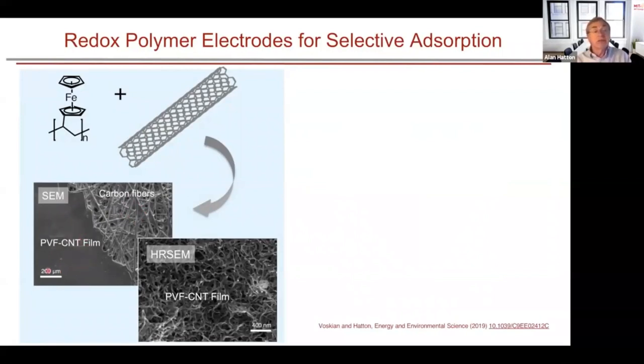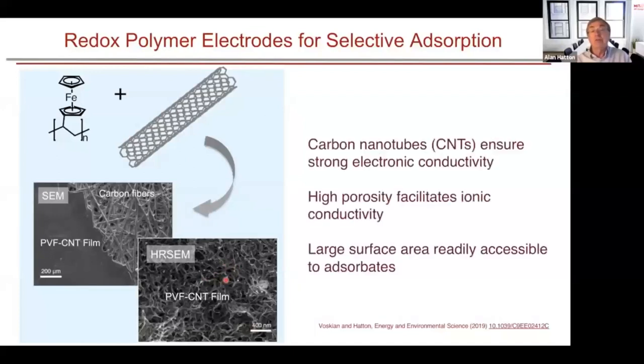films shown here. This scale bar is 200 microns. If you zoom in a little bit closer, we've got a 400 nanometer scale bar here. You can see it's a very porous structure. You can see all the carbon nanotubes here. These are coated with the ferrocene, so you get very large surface areas and a large porosity, which is good from a number of perspectives. The carbon nanotubes themselves ensure strong electronic conductivity. The high porosity facilitates ionic conductivity because we have these electrodes that are bound with an ionic liquid. And the large surface area makes them readily accessible to adsorbates such as CO2 in this case.